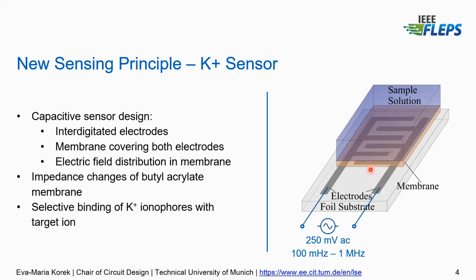It is important to mention that the thickness of the membrane is a critical point. The larger the electrode dimensions, the thicker the membrane needs to be, because we want all of the electric field distribution inside of the membrane and not inside of the electrolyte, because then we get a better selectivity and sensitivity of our sensor.